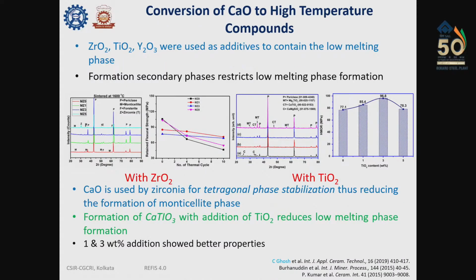In the second approach, we have used additives like ZrO2, titania, and Y2O3 with the aim that these will react with CaO and reduce the availability of CaO in the system and thereby control the low melting phase formation. In the case of zirconia, you can see this CaO is used by zirconia for its tetragonal phase stabilization, as well as it forms calcium zirconate, and thereby it reduces the monticellite phase formation. In the other case, when we are using titania, it reacts with calcia and forms calcium titanate, so the CaO is not available to form the low melting phases.